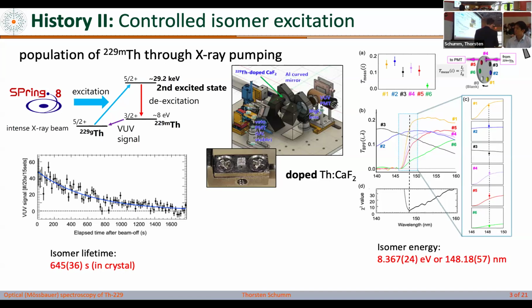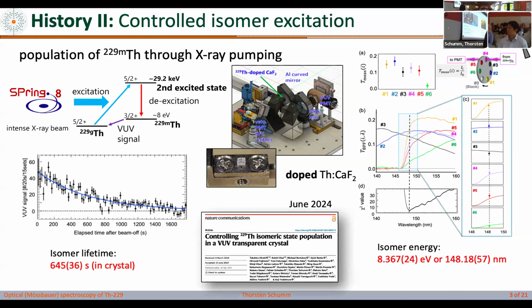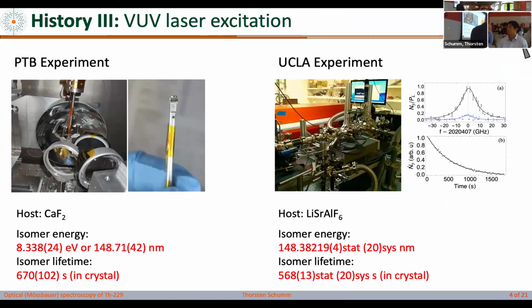This was done quickly after in the two experiments that were mentioned, one performed at PTB in Germany and one performed at UCLA. Conceptually, they are almost identical, both using crystals, with different host materials. This one is calcium fluoride, very much like this one here. This is our crystal. UCLA uses a more complex material, lithium strontium aluminum fluoride, another classic in VUV optics. But otherwise, it's the same thing.